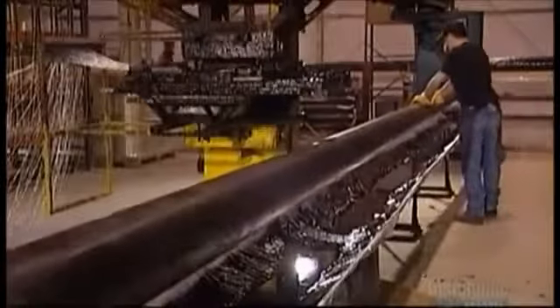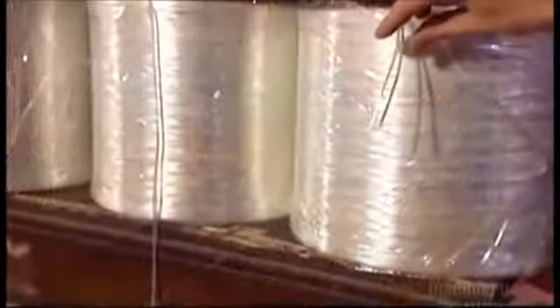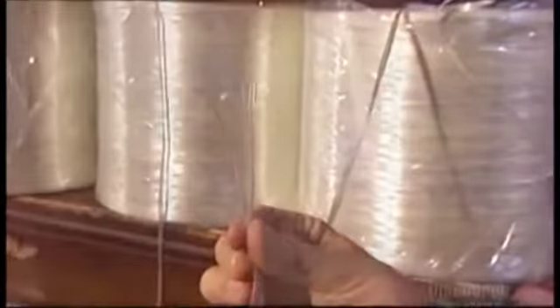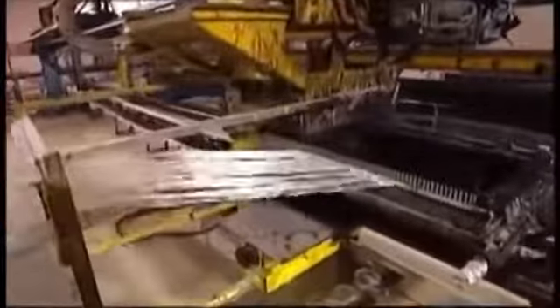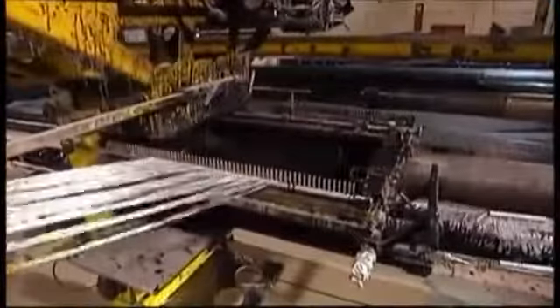These streetlight poles are made of what's called composite, a combination of fiberglass and epoxy resin. Epoxy resin is a gooey liquid plastic mixed with a hardener. The factory constructs each pole on a mandrel, a long tapered metal cylinder. Workers first lubricate the surface. Then they take what's called fiberglass filament, a string composed of 2,200 tiny fiberglass strands. They'll wind dozens of filaments around the mandrel to create the pole. But first, the filaments go through a bath of epoxy resin. This resin is moldable, and once it's heat-cured, maintains its shape.